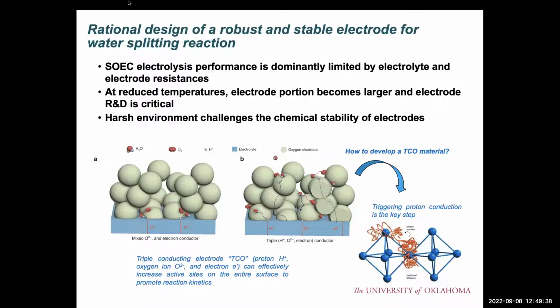of the active site. So how we are going to trigger the proton conductivity in the oxygen electrode is very important. Normally, proton conduction comes from the formation of the proton defect. The proton defect is a defect reaction between the oxygen vacancy in the lattice and the steam. When the steam fills the site of the oxygen vacancy, it can create hydroxide in the lattice, and this hydroxide species can be established to form a bridge for the proton conduction. So in order to trigger the proton conductivity, we also want to hydrate the oxygen vacancies in the electrode materials.